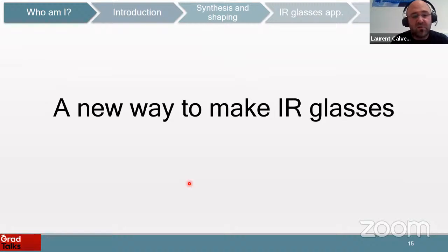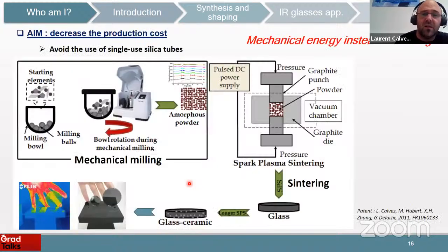But we developed several years ago a new way to make infrared glasses, but not only infrared glasses. Different kinds of glasses can be made using this technique. So instead of using heating, instead of using high temperature, we have decided to use mechanical energy. It's pretty interesting because, using this energy and this technique, what we wanted to do is to avoid the use of single-use silica tubes, because I told you we have to break them each time.